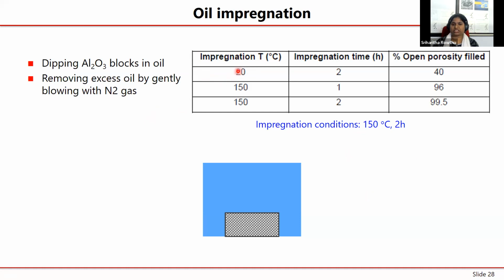At 20 degrees Celsius, this is your specimen, your porous alumina block, and if you dip it in this oil, which is a high viscosity oil at room temperature, and leave it for 2 hours, obviously because this oil likes aluminum oxide, through capillary action the oil will go through the pores, but only 40% of it was filled. This I got by simply weighing the sample before and after and comparing it with the open porosity volume that the sample had. So only 40% was filled.